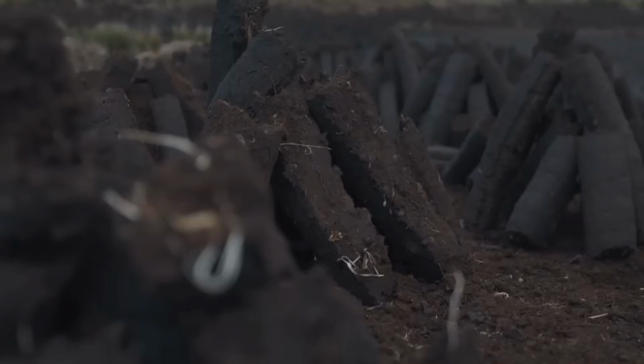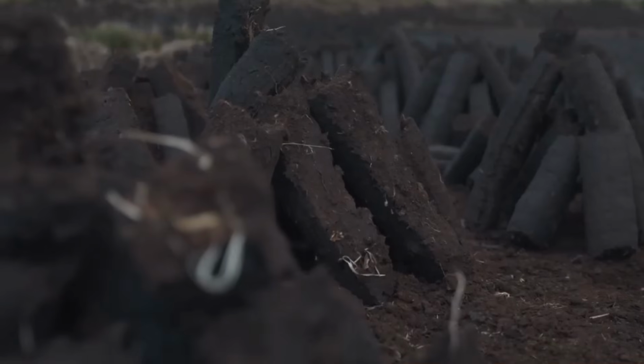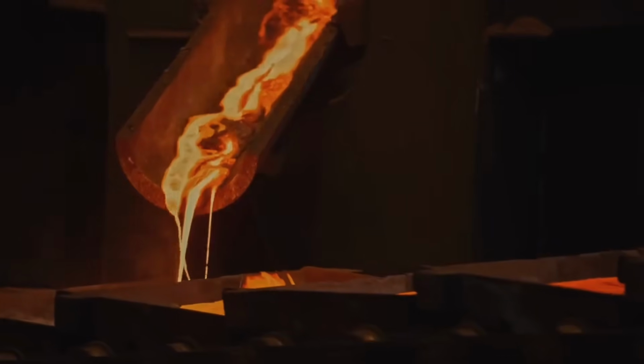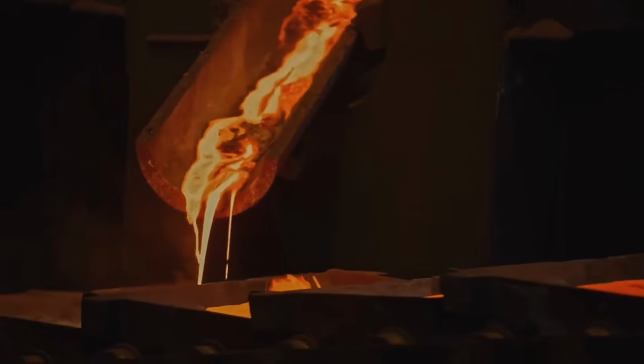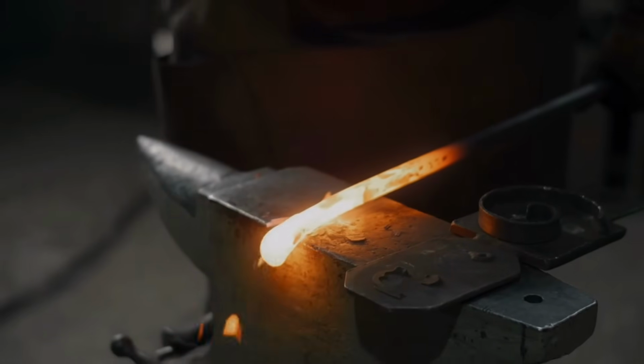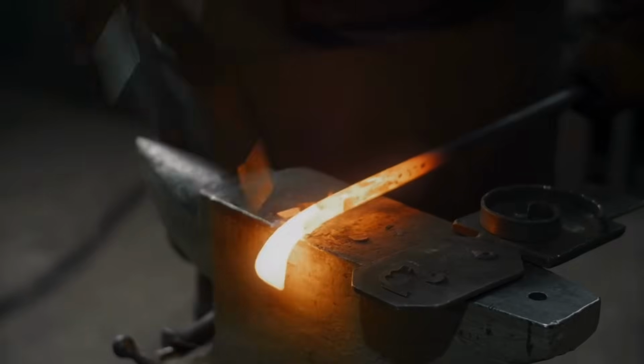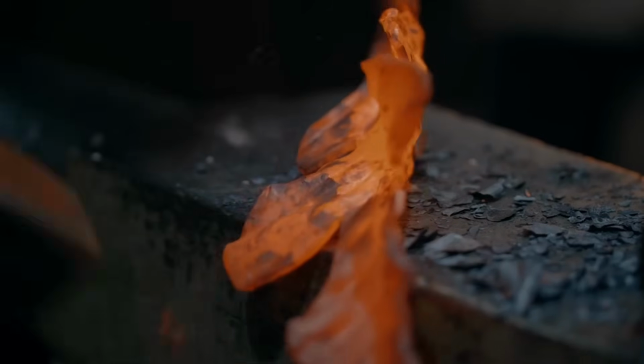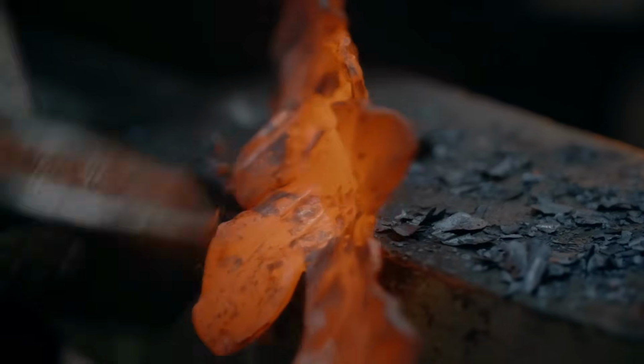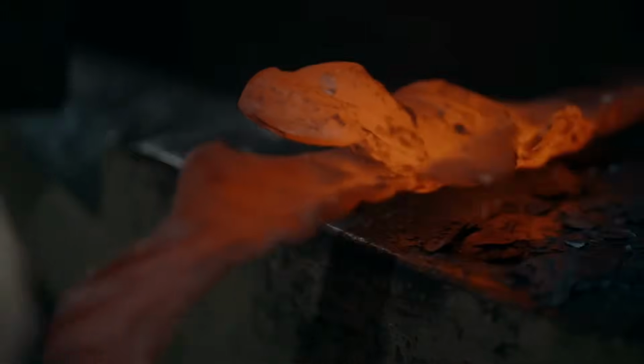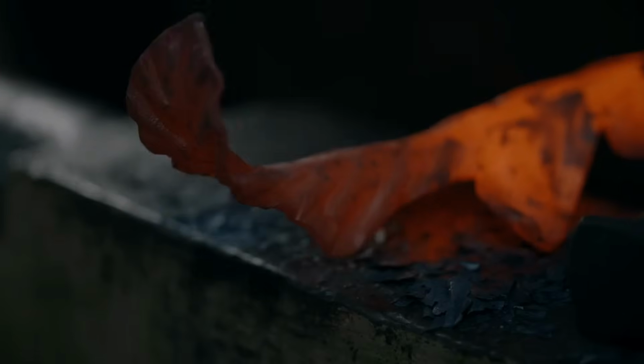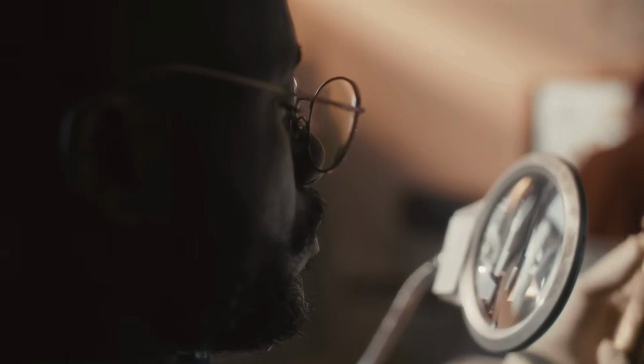You now have all three ingredients: a renewable ore source rich in phosphorus, a low-temperature smelting process that preserves slag, and a forging method that distributes those inclusions evenly. Take any one away and you do not get the same result. Combine them and you get a metal that, buried in the same waterlogged environment that produced its raw material, can sit for a millennium with very little degradation.